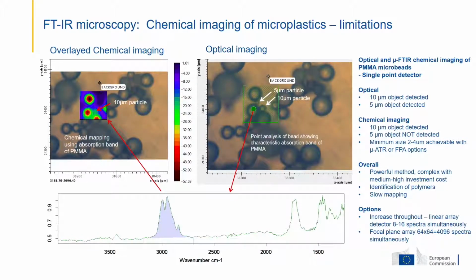The particles were PMMA, not polystyrene. Comparing the optical and chemical images shows that particles around about 10 microns in size can be distinguished, while smaller microplastics, although visible in the optical images, cannot be detected in the chemical image. This illustrates one of the main limitations of FTIR, which for routine measurements would be limited to sizes around 10 microns, but for practical purposes and speed of measurements, a size of 15 to 20 microns would be more realistic.